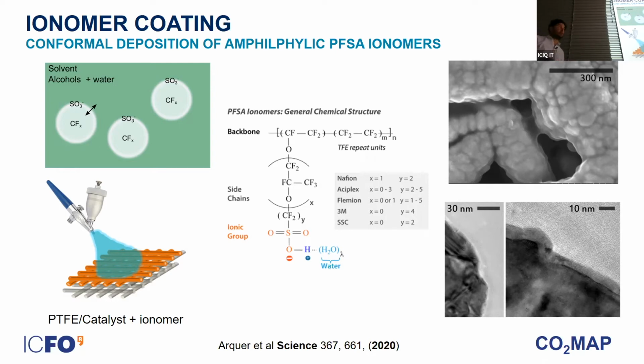These polymers are polar. You have a polar group here and a non-polar group here. So we thought, okay, how can we deposit this on top of the copper carbon gas diffusion electrodes that you have seen in the previous slides? So we mix these polymers with some alcohols and water, polar solvents, in such a way that we hope we could play with the way these polymers will self-assemble when deposited in the final film.